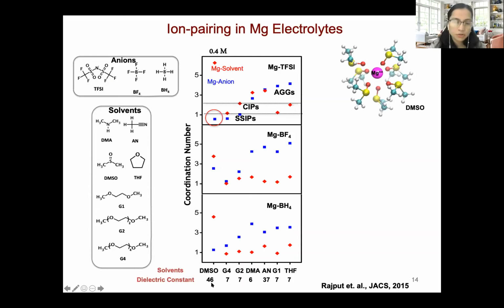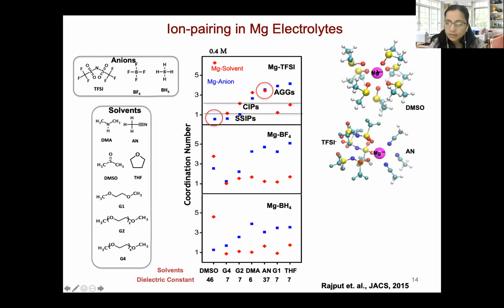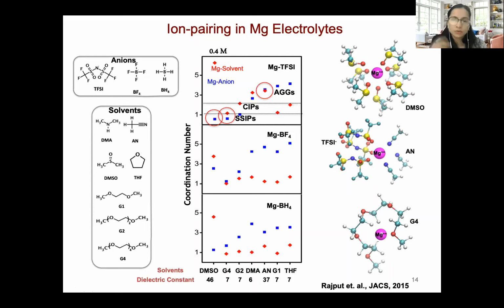Some of the high dielectric constant solvents like DMSO provide very strong solvation and can separate magnesium from the anion because they bind with this polarizable oxygen atom. On the other hand, other high dielectric constant solvents such as acetonitrile fail to do so and result in formation of aggregates. An interesting trend was observed here for glymes, which show a very low dielectric constant of 7, but they have the ability to basically wrap around magnesium ions, and they have high oxygen donor density, due to which they are able to basically dissociate magnesium from the anion. And for the anions, we found a trend that if you have a bulkier anion like TFSI, it has a lesser degree of ion pair formation compared to the smaller molecules like BF4 and BH4.